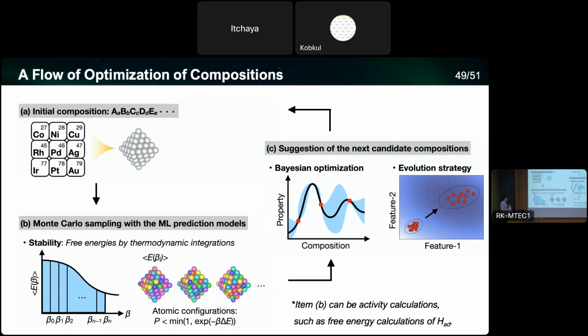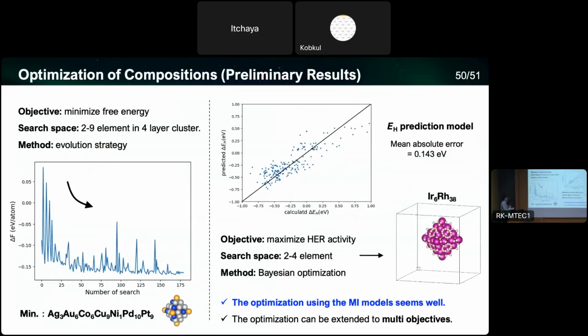And in the case of reactivity, we can maximize the reactivity to get the best composition with specific configurations. Then this is some of the preliminary results of our optimizations. So the left one is the minimization of free energies, considering up to 9 elements in the 4-layer clusters. And the free energy is decreasing as the number of such increasing. And finally, at this moment, we got this, which is probably the most stable one.